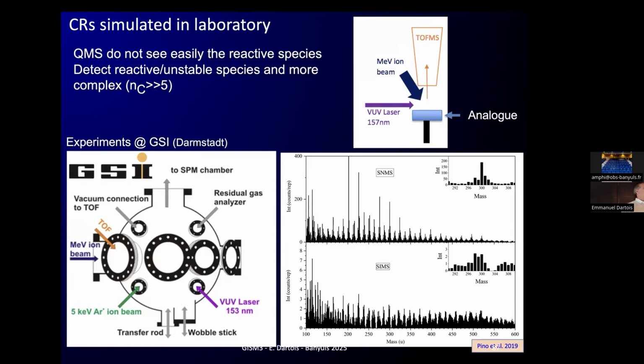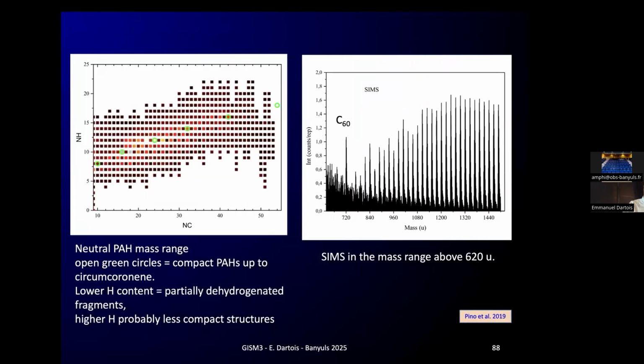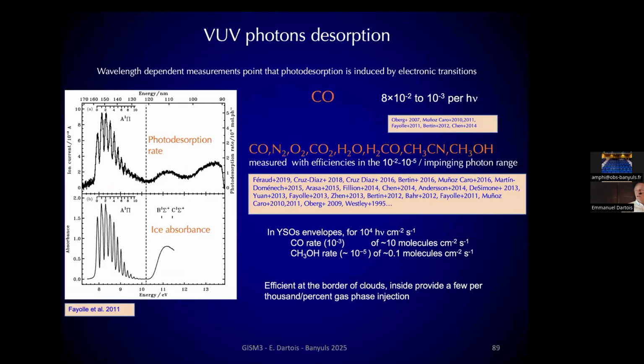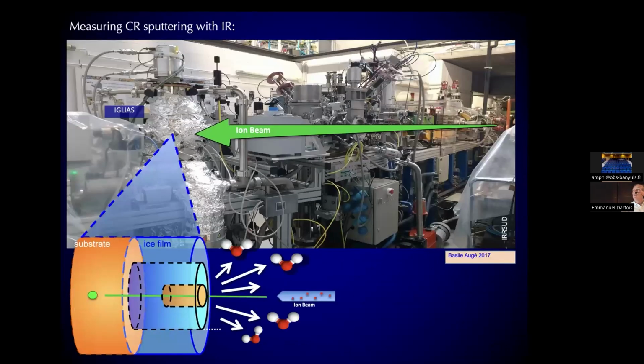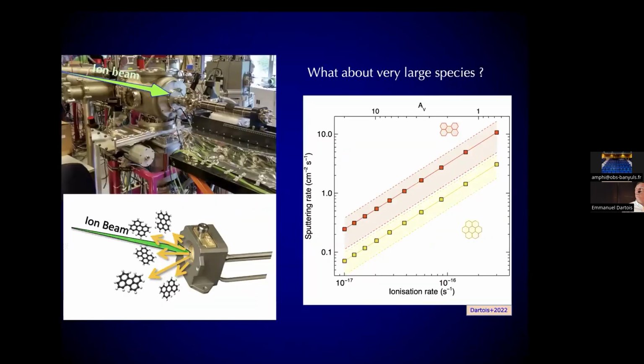Now it's important to do this experiment to try to have a kind of absolute cross-section that you can later give to modelers to see if it's feasible, or if it has a meaning or not. This is an example of one of the experiments we made, where you can see that in some cases you can even eject a species with 60 to hundreds of atoms, not in huge quantities, but still you have a mechanism where you can produce these species by impact with a cosmic ray. Photodesorption, the influence of UV photons, you can have a look also experimentally. Again, it's movie time. You can do the same for cosmic ray sputtering and put this into models.